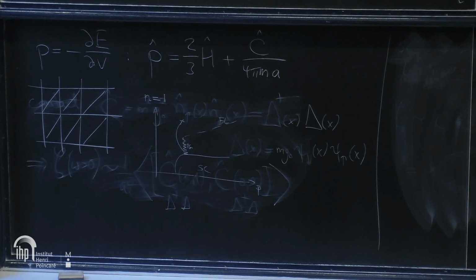Any more questions? Maybe I'll have a follow-up because I asked something similar during your talk. The symmetry of the order parameter in those systems, you said that it was not, of course, standard S kind of stuff. There's some anisotropy, but now you mentioned that it's potentially D-wave. The theoretical calculations that several groups have been doing yield a D-wave superconducting state. Experimentally, I don't think this issue is completely settled.